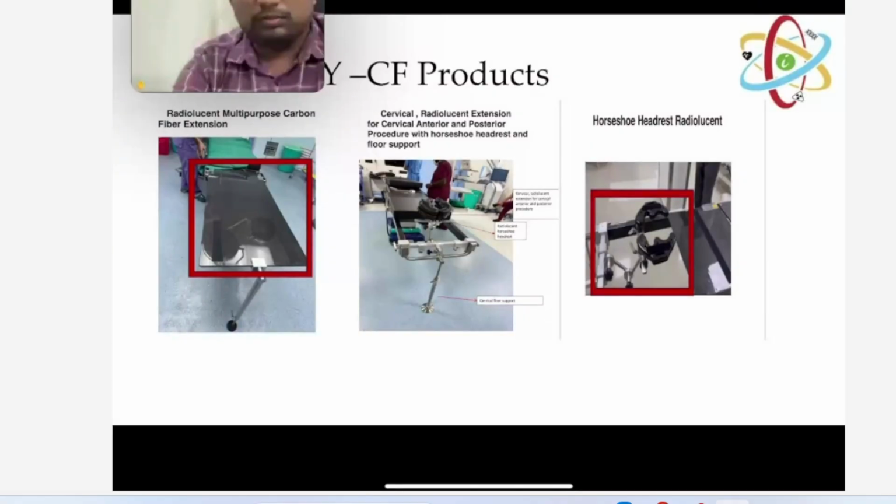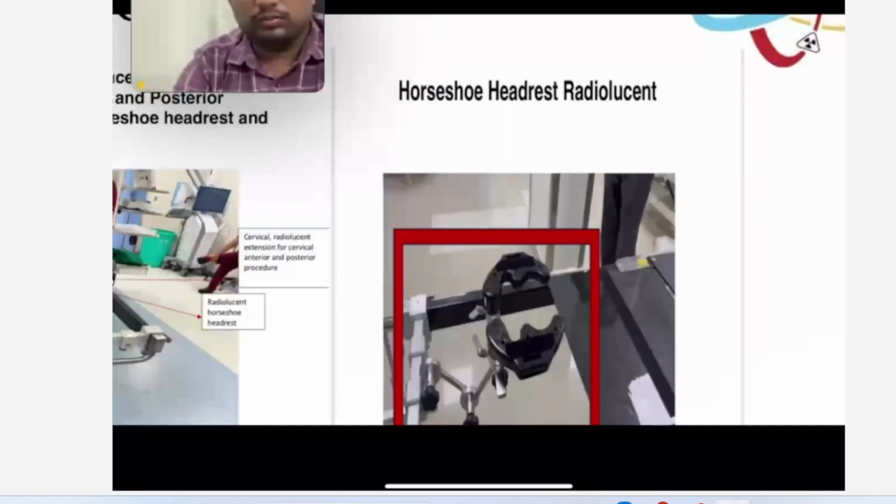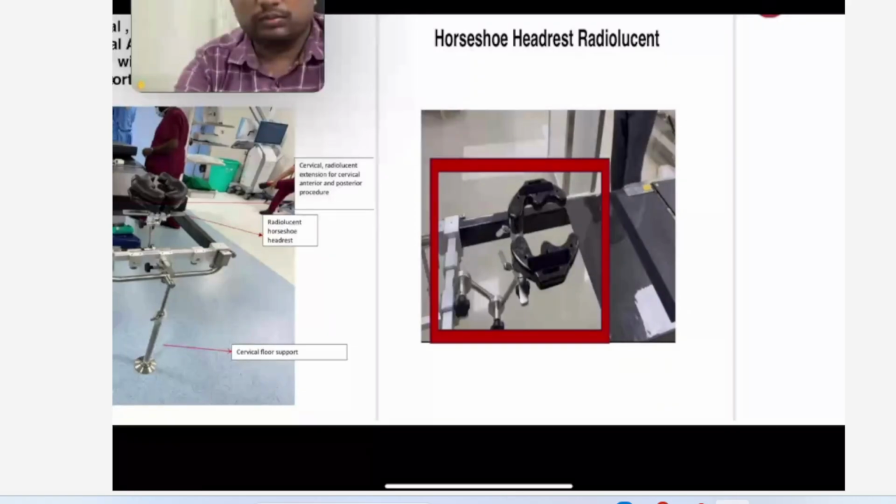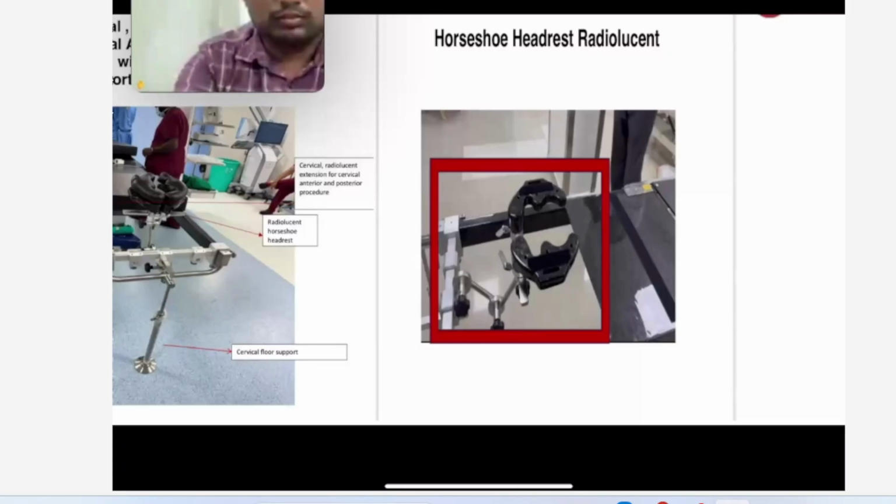These are the three products I've shown you. The last one, which Arshu addressed, is developed purely from the cut waste material. I keep it safely, and again I make it into small pieces. Then I do forging. Forging is nothing but mixing in some chemicals like resins. I create a mold or die, depending on the application, and compress it. I leave it to cure, and once it is ready, I do some machining and finishing work. Then it is ready.